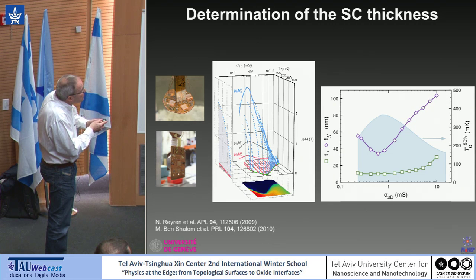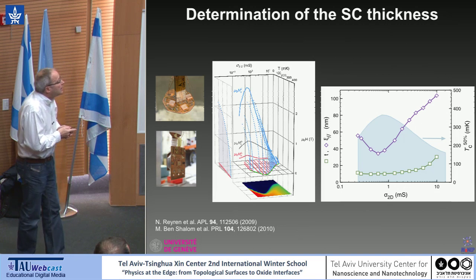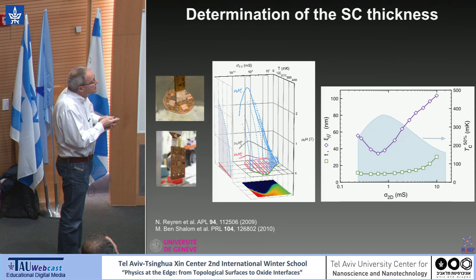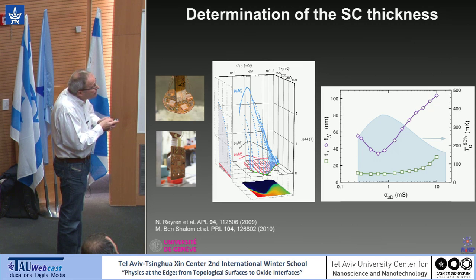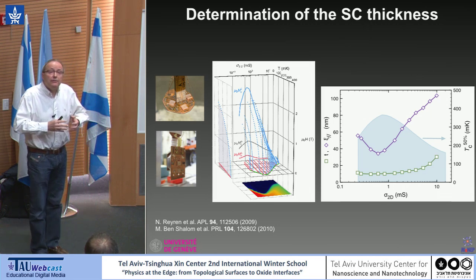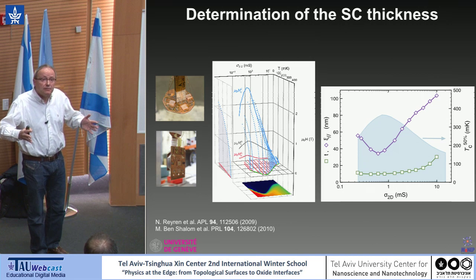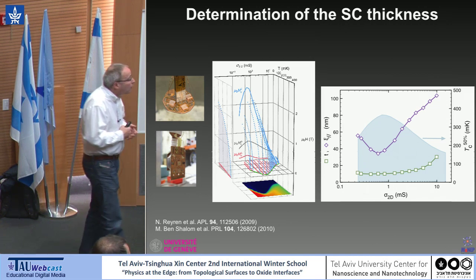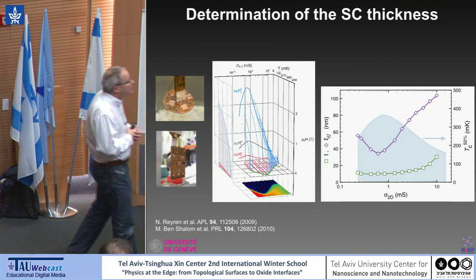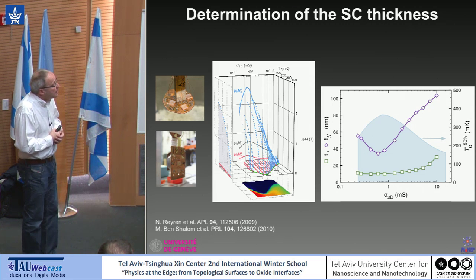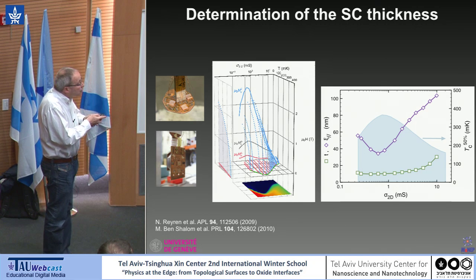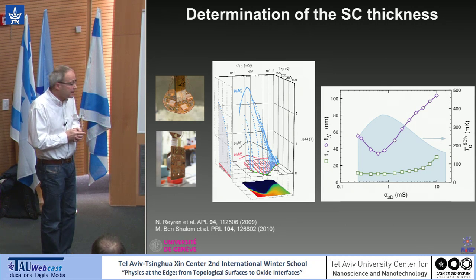And for each of these points, we went through perpendicular and parallel field measurements. And the result is shown here. In green, this is the thickness versus doping, which is given here in conductance. So 10 nanometers, but you see here, as you go in the overdoped regime, the thickness is increasing. And we know this for quite many years, but we only reproduced the data recently. So now what we have to do, for each of these dopings, is divide by the thickness.